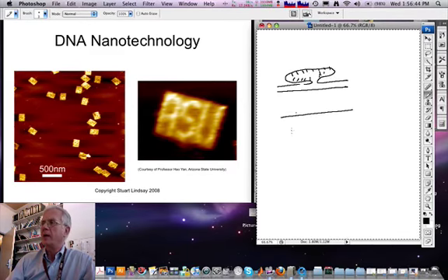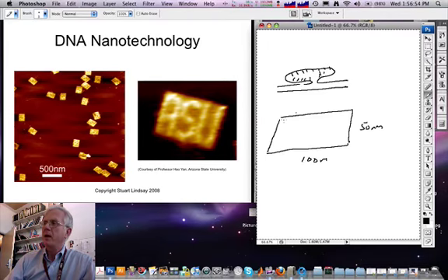So we have made devices in which, so this might be about 50 nanometers, and this perhaps 100 nanometers, in which the pixels like this are used as a barcode for identifying a particular chip. And then over here are single strands of DNA that, when they hybridize their target, become rigid, so show up in the atomic force microscope as a high point on the device.